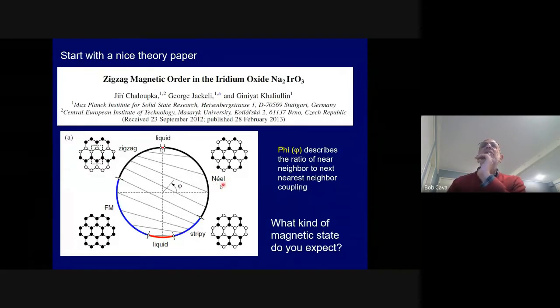People started this. Khaliullin is a person who has a lot to do with my research after this. So if you look on a honeycomb, if you just don't worry about sophisticated electronic models or magnetic models for honeycombs, it was already known that there were 4 types of magnetic ordering in honeycomb lattices at low temperature. One is typically called Néel ordering, where each spin has a neighbor with the opposite spin configuration. Then you can have stripy, where you might have two that are ferromagnetically coupled and antiferromagnetically coupled to the next 2. You can have all ferromagnetic, you can have zigzag.